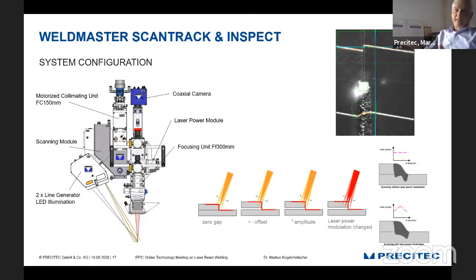So again, a Precitec own built device with a 1D scanner. And what we can do easily with that 1D scanner is to oscillate the laser beam. For those who also are a little bit familiar with laser welding know that some of the applications do need a stable keyhole, and you can stabilize the keyhole by very fast oscillation of the laser beam. And also, if you do lap welding, what is displayed here, it sometimes helps if the gap is varying, that you are able to oscillate the laser beam in order to bring some material from the top sheet to the bottom sheet. And this all is possible with the WeldMaster ScanTrack with all the inspection and monitoring systems.